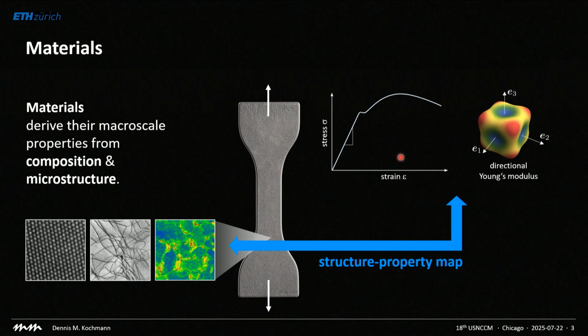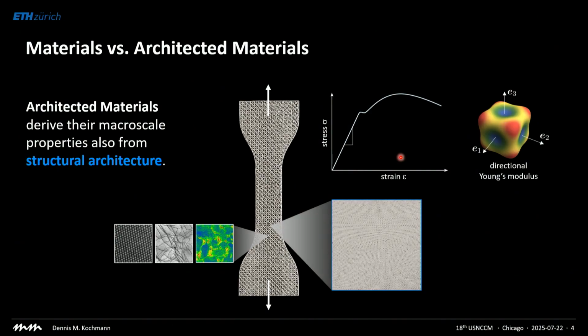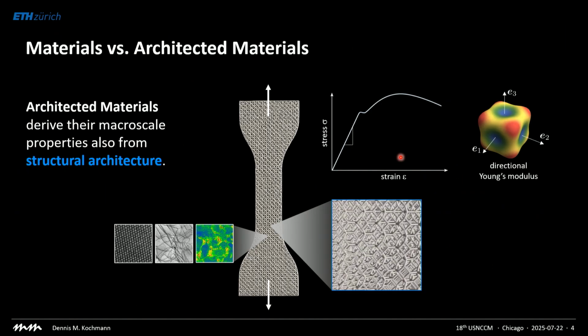There's nothing fancy here. When you turn to architected materials, you introduce one more level. And this level in the middle has structure. This structure is literally a structure, which means if you zoom in, you find plates, beams, shells, something that we can describe with structural mechanics. And all of a sudden, the main relation that we're trying to understand is how to go from this structure to the macroscopic properties. Of course, the whole thing is still made out of an actual material by the end of the day. But once you know the base material properties, and these we can characterize relatively easily based on dog bone specimens, it's the structure that determines the ultimate properties. And this is what we're trying to understand.